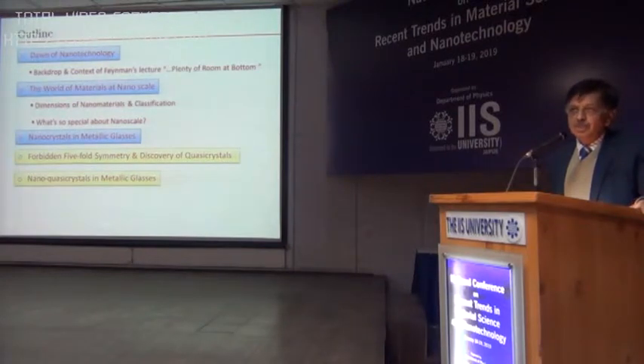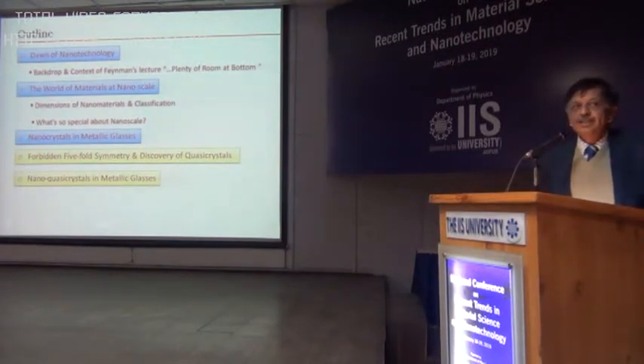Otherwise, what will happen if you heat it slowly, then the crystals get time to grow. So when they grow, you have the usual crystalline materials. So basically, the term which is used is called annealing. It's just like if you set a target temperature for a system to heat, you set your furnace at that particular temperature, and then introduce the material inside it, of course in a controlled atmosphere, or you seal it in a quartz ampoule with vacuum, so that it doesn't oxidize, because most of the systems I will be talking about are prone to oxidation.